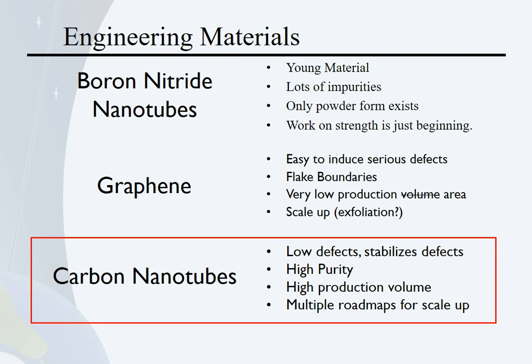So of the three, my pick is carbon nanotubes. I do think boron nitride has a place, especially for dealing with radiation and oxidation. Graphene, maybe as a protective coating, or as some sort of repair material, or in other devices, but I'm just not seeing that coming out of the research. So if I have to back a single horse, carbon nanotubes is it. Though I would expect to see some sort of composite with some other protective material, and boron nitride nanotubes do seem like a good fit for that.